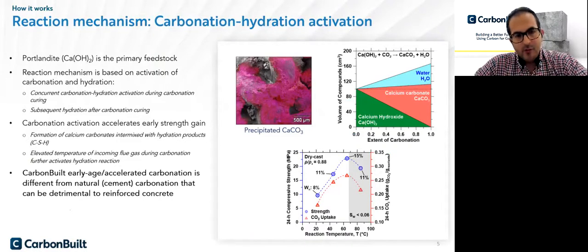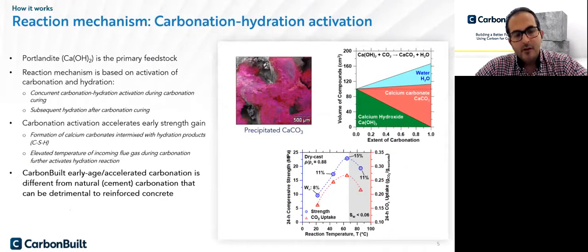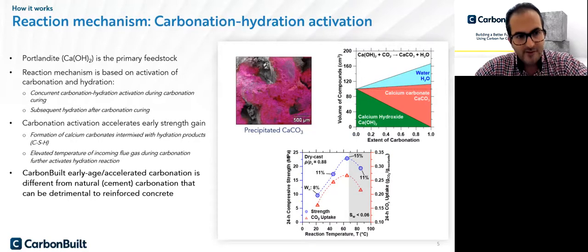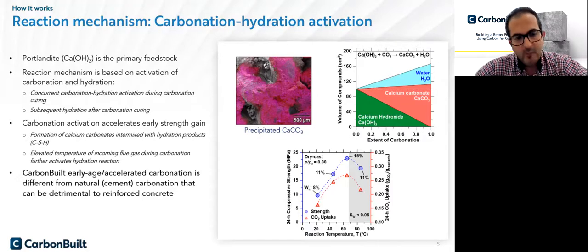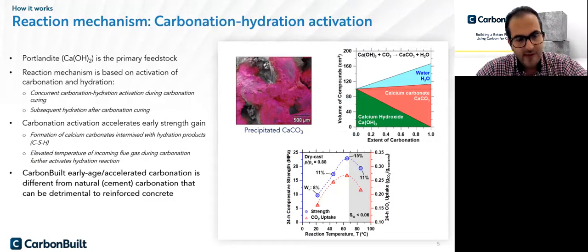Regarding the reaction mechanism of the CarbonBuilt technology: portlandite is the primary feedstock. It has a high tendency to get carbonated, and when it reacts with carbon dioxide it forms limestone, which can offer cementation in concrete. Because of the increased volume during this reaction, it also refines the porosity. This reaction mechanism is based on the activation of carbonation-hydration. During carbonation curing, we have simultaneous hydration and carbonation activation, and after the carbonation curing process we have a subsequent hydration process as well.